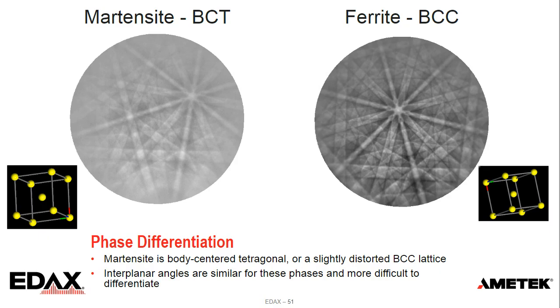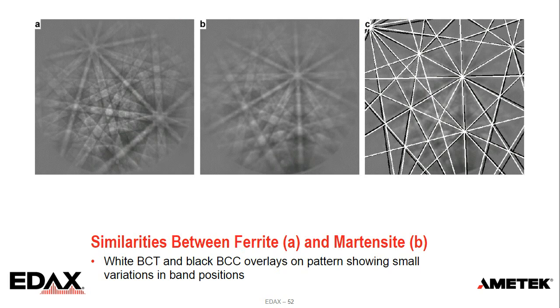And this just shows an example of this. So there's our ferrite martensite patterns again, but on the image there for the martensite pattern on the right, the C image, it shows the white martensitic overlay and the black ferritic overlay onto the same pattern. And you can see the places where the white and black lines are essentially lined up, and the shifts between them are very small. So they're very subtle shifts between the two. So it's difficult for the Hough to reliably differentiate. It can always differentiate, but it's not always 100%.